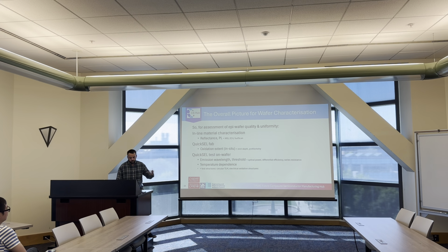So the overall picture for wafer characterization then, I just want to draw attention to some of the things I haven't mentioned that go on. There's inline material characterization. I talked about reflectance and PL, but there's also X-ray diffraction, electrochemical capacitance voltage to assess the doping concentrations, surface scan for defects. Then we've got the fabrication of devices across a wafer. Talked about how the oxidation extent might vary. There's also etch depth variations that are measured, profilometry, so of the metal contacts.